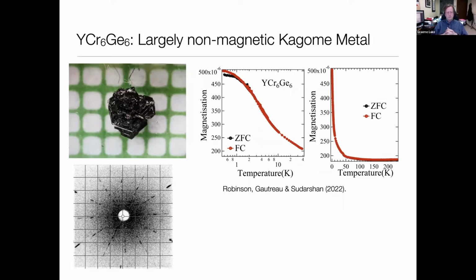Those measurements were done on materials made by our collaborators at the University of California. We started a project now up in the Center for Crystal Growth on the 4th floor to look for new Kagome metals. One of the ones we've come up with is yttrium chromium 6 germanium 6. Everything is nominally non-magnetic. Although the susceptibility is non-zero, it corresponds to a very weak magnetic moment of less than 0.2 Bohr magneton per unit cell. There have been other materials in the series where the yttrium is turned into, for example, holmium or some other rare earth, and they become very magnetic.